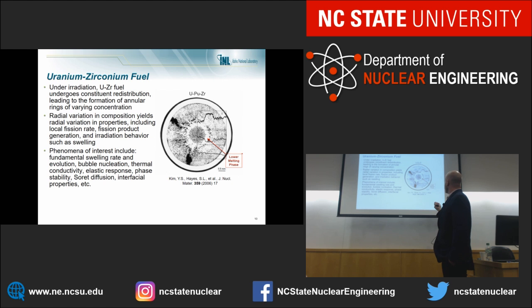So here are these curves. This is electron micrograph data, I think, where we're showing the composition of various elements in a U-Pu-Zr fuel pin. So here's our plutonium content. That's about uniform throughout the system. However, we're seeing an enrichment in the interior zone of the fuel of Zr. We're seeing a depletion in an intermediate zone, and then about the as-fab composition of Zr on the exterior.